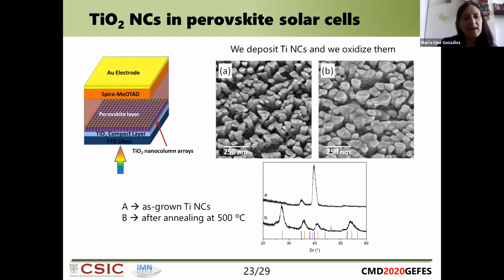So because one of the most used layers for the electron conducting layer is titanium dioxide, we thought, why not introduce titanium dioxide nanocolumns in that part, in such a way that with them we could enhance the scattering of the light and then increase the absorption of the light inside the perovskite, so as to increase the efficiency of our system.